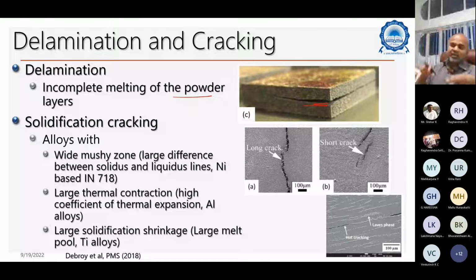Right? If they are not concomitant to each other, then you're going to end up with incomplete melting of the powder layers. Incomplete melting of the powder layers leads to a certain kind of cracking at the junctions. Okay, this is one layer and this is one layer, and the material is actually cracked between these two. So that is a delamination. It gets completely delaminated.